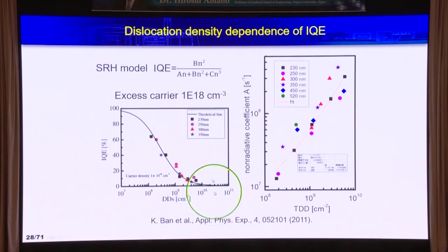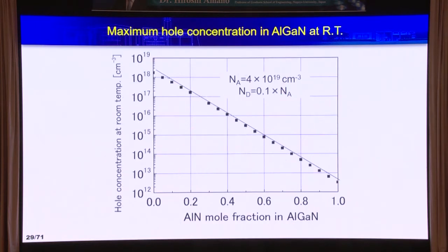So, by reducing the dislocation density, DD, the IQE can be increased. According to the Shockley-Read-Hall (SRH) model, this term can be minimized by reducing the threading dislocation density. That's the one thing. And the second term, hole concentration. It is not easy to increase the hole concentration. There is a fundamental limit.